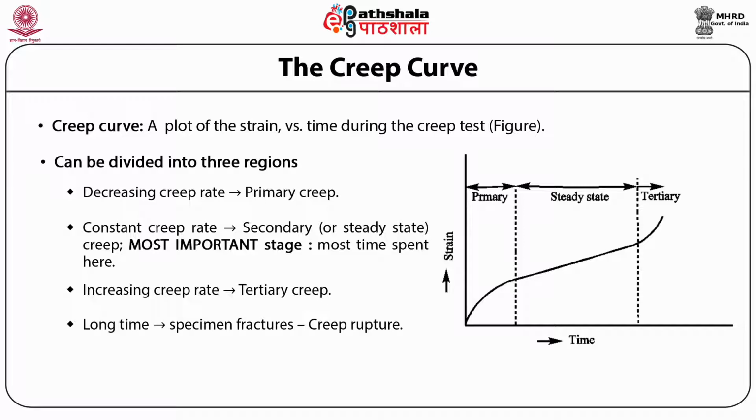It should be noted that in a given creep test, not all the stages may be observed. The shape of the creep curve depends on the material and the testing conditions, that is time, temperature and environment. Furthermore, the part usually spends most of its life in the steady state region, which is therefore the most important of the three stages.